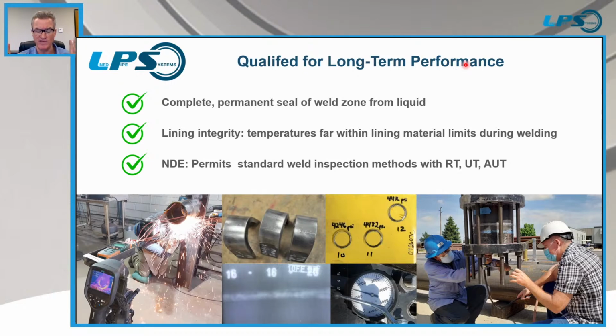Also integrated into our design, it's a flexible design, so it takes into account pipe out of roundness and fluctuations in pipe inside diameter. The lining integrity: we've done extensive testing, and you'll see some of it. I think we just did see some of that. Some of the testing we've done on the inside, and our design is again an innovative design that really keeps the temperature from affecting either the sleeve or ring lining, and also the holdbacks on the parent pipe lining are farther back from other solutions. So the weld temperature does not come close to affecting the integrity of the lining.